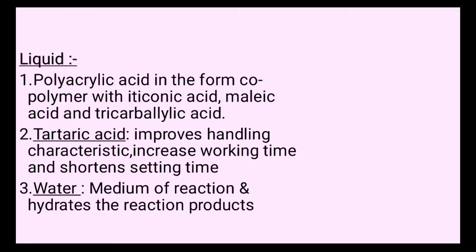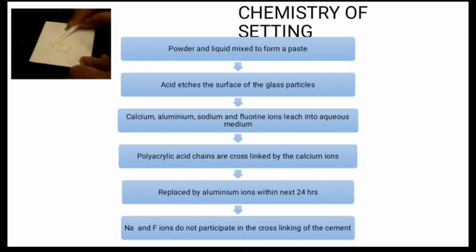The liquid form includes polyacrylic acid as a co-polymer with itaconic acid, maleic acid, and tricarballylic acid. It also contains tartaric acid, which improves handling characteristics by increasing working time and shortening setting time. Water is also included, which acts as the medium of reaction and hydrates the reaction products.